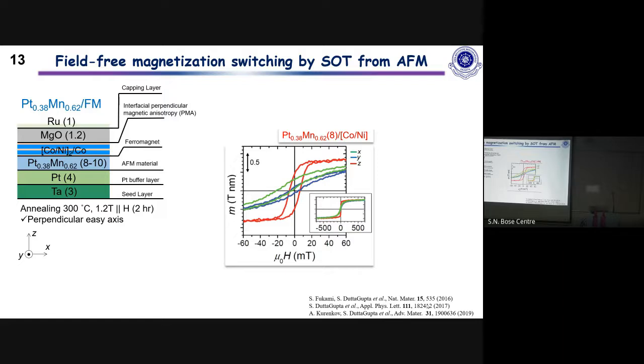Why do you need the capping layer? Actually, MgO is hygroscopic, so it absorbs water, and you also need MgO to have a perpendicular magnetic anisotropy. But if you keep MgO as it is, it will start absorbing water. So you cap it with something which doesn't kill you.